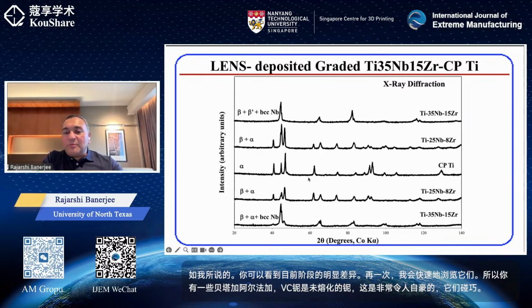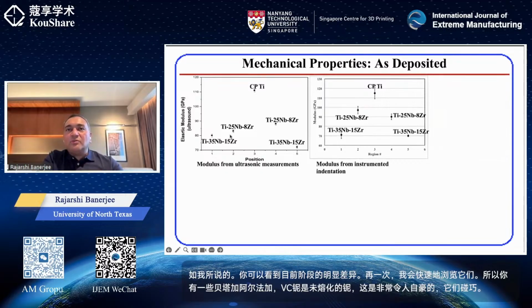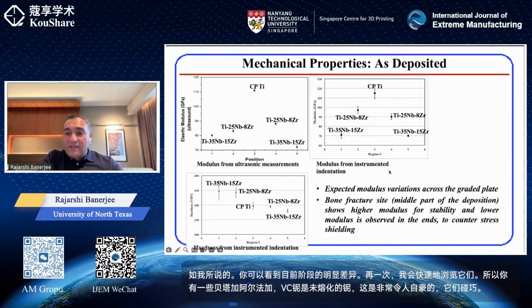But the corresponding change in modulus, which we measured with 2 independent techniques, this is from the ultrasonic measurements. So at the edges, the modulus is going down to the range of about 72, 73 to 80 GPa using ultrasonic. If you look at it from instrumented indentation, again, it's pretty similar, 70 GPa, whereas at the center, the values are as high as 110, 115 GPa. And this is nicely grading on both sides. It's a symmetrical gradient as you would want for an actual fracture fixation plate, with the central region nicely shielding the fracture site, but the edges have lower modulus. So this worked as we wanted to design it, and it is the design of the modulus.